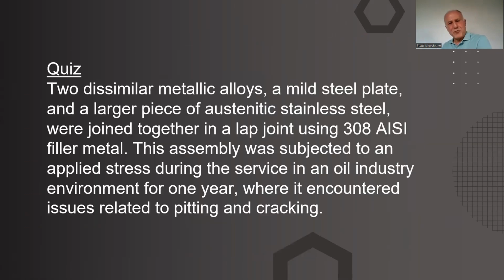So that was the quiz I prepared. You can look at it later. So for example, how do we understand this? Two dissimilar metallic alloys. So it shows what that means. A mild steel plate and a larger piece of austenitic stainless steel were joined together in a lap joint using 308 AISI filler metal. This assembly was subject to an applied stress during service in an oil industry environment for 1 year, where it encountered issues related to pitting and cracking.